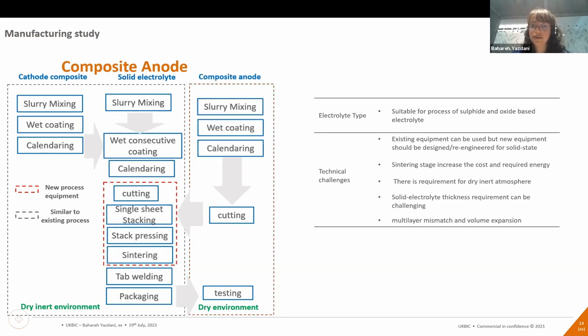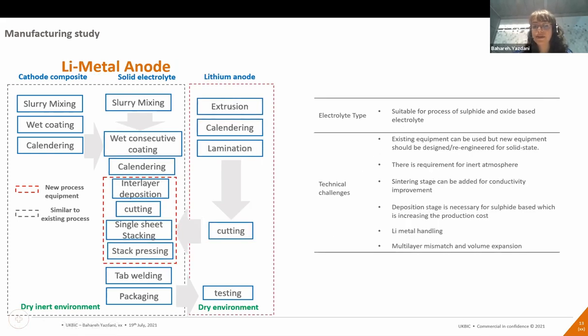And for composite anode, we can use a silicon graphite composition on the anode side. Again, it's the same. The slurry manufacturing can be very similar to the cathode composite manufacturing, followed by preparing the cathode plus solid electrolyte layer, which we call the catholyte layer, and then on top of that, adding the composite anode as a third layer. However, for the anode in this format, there is probably more need for sintering and high temperature manufacturing, because it can be suitable for oxide-based as well. In the previous format, it might not be needed to use high temperature sintering because it's more adapted for sulfide-based as well.